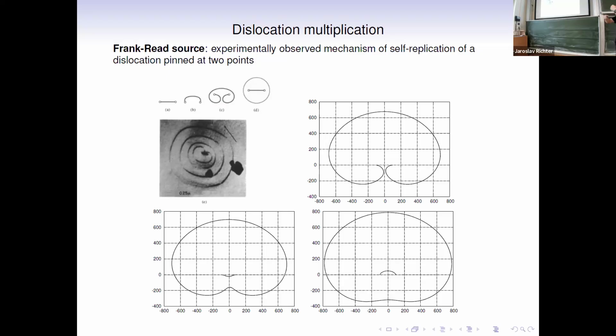So this is a self-replicating mechanism which goes along as the material sample is under loading. Here there are 3 simulated snapshots: right before the splitting; right after the splitting, making one single dislocation loop and one loop with 2 fixed ends, which tries to bow out again; and the third stage, when the story continues.